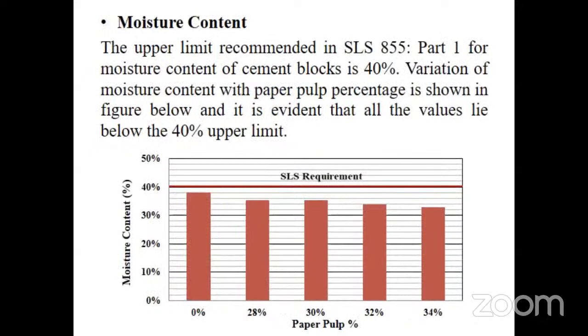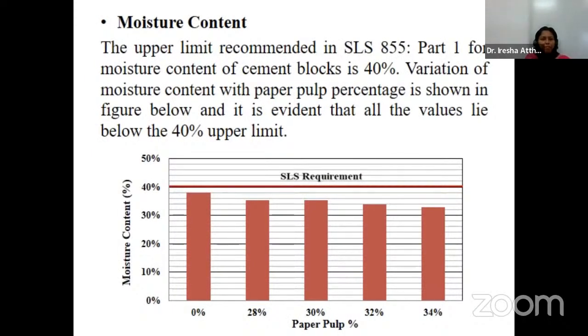Next test is the moisture content test. It was carried out conforming to SLS 855 Part 2 of 1989. The upper limit recommended in SLS 855 Part 1 for moisture content of cement block is 40%. Variation of moisture content with paper pulp percentage is shown in this figure. According to the figure, all the values lie below the 40% upper limit.